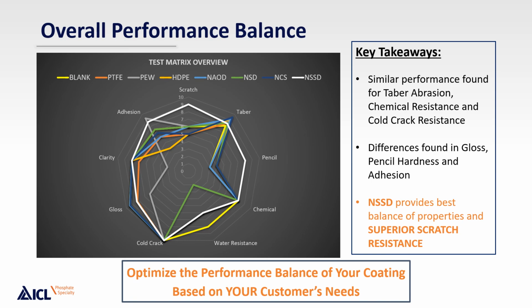So combining all the tests into one spider diagram really gives you a good visual display of how all the additives impact performance. In some cases, the performance was very similar between all of the additives, and these tests could be seen in such as Taber abrasion resistance, chemical resistance, and of course cold crack resistance, where all of the coatings passed. But really the areas that we're looking for is where is their differentiation, and that can be found in, of course, the gloss, pencil hardness, adhesion, and the property of focus, scratch resistance.